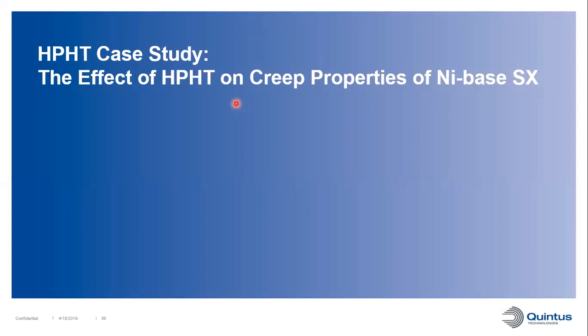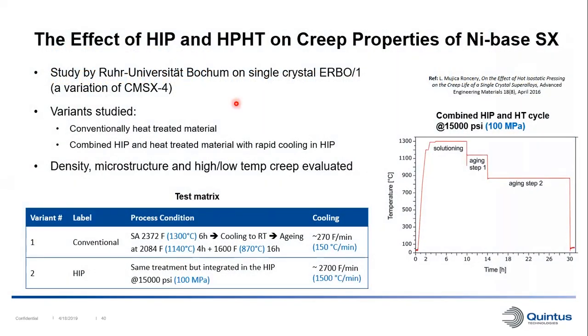And now I want to show a case study for high pressure heat treatment, and this is the effect of high pressure heat treatment on creep properties for nickel-based single crystal casting. So this study was performed by Ruhr University of Bochum in Germany. This university has a HIP system from us with the very fastest quenching capabilities. And they were looking at a single crystal alloy called ERBO/1, which is a similar alloy to CMSX-4.